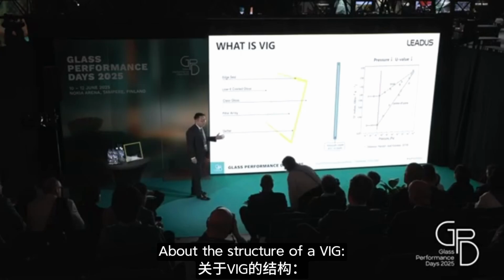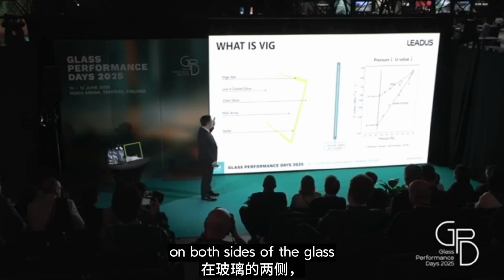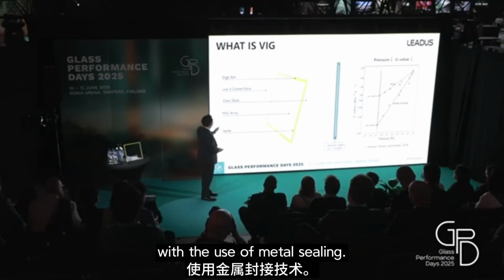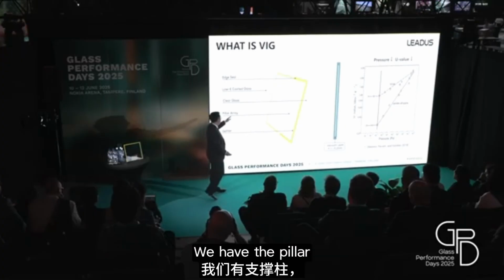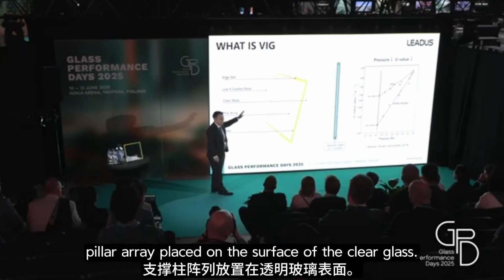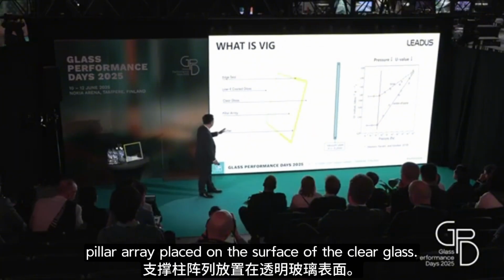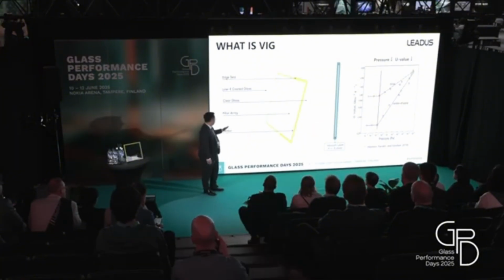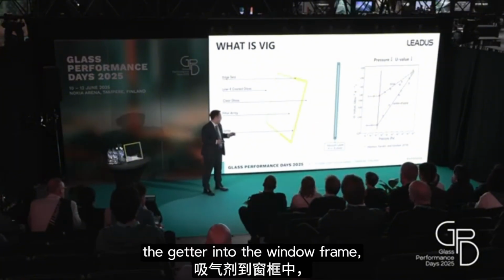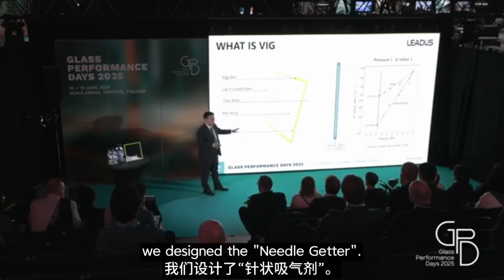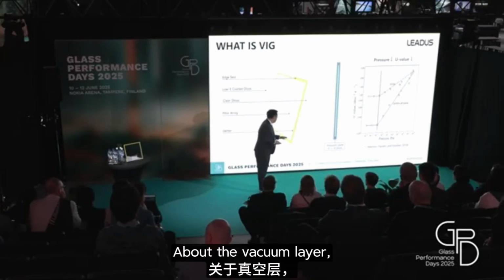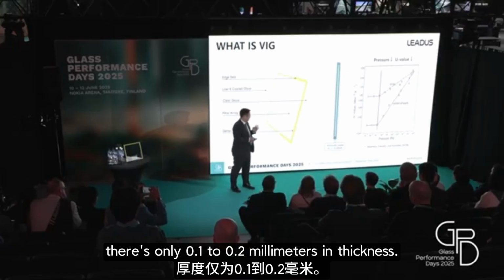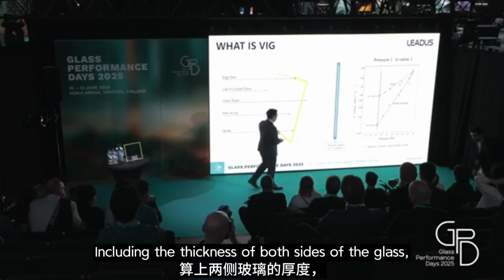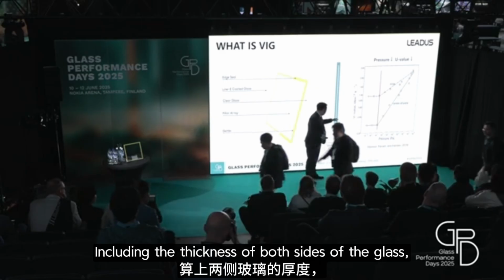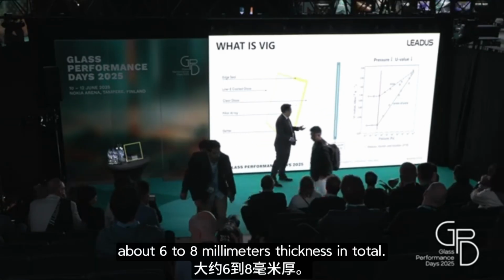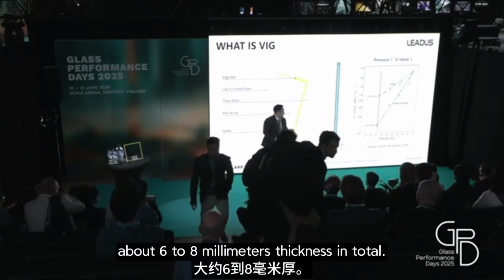About the structure of a VIG, we have edge seal on both sides of the glass with the use of metal sealing. We have the pillar array placed on the surface of the clear glass. And in order to hide the getter in the window frame, we designed the needle getter. The vacuum layer is only 0.1 to 0.2 millimeters in thickness, and including both sides of the glass, there are only about 6-8 millimeters thickness in total.